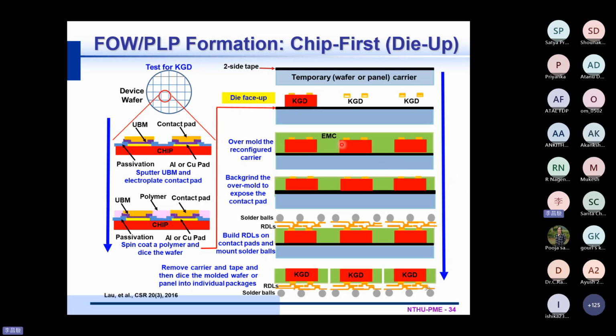Why? When we fill in the epoxy molding material at high temperature and cool it down to room temperature, the total wafer or panel will be warped. So when we back-grind the EMC material, you can see that at the edge, the chip will be ground more than at the center location.